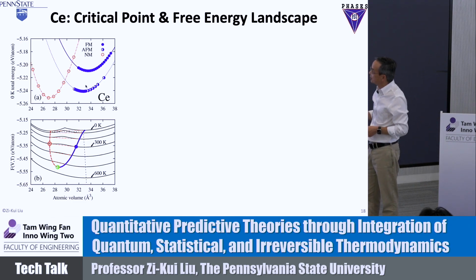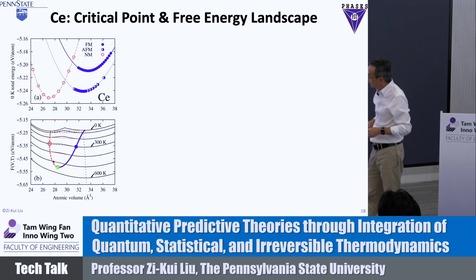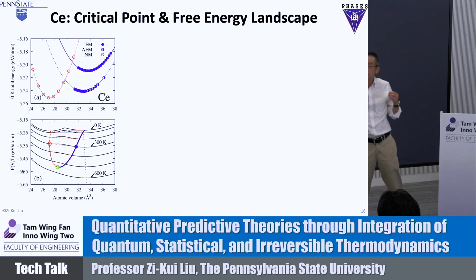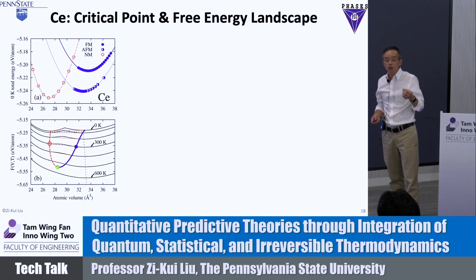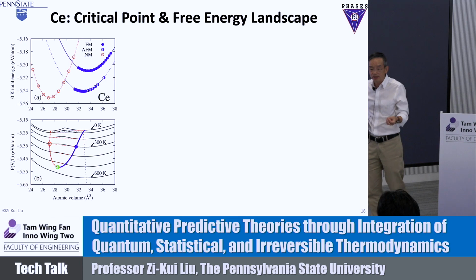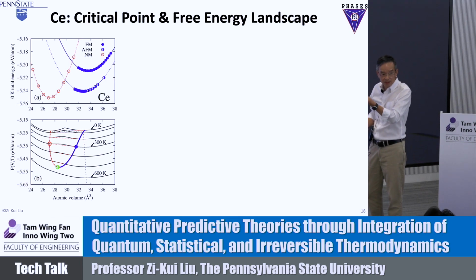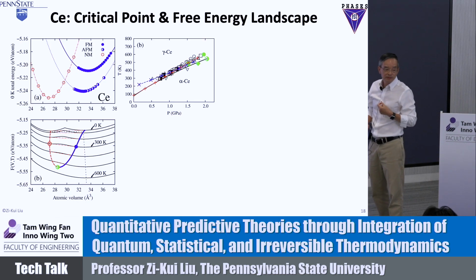With only 3 configurations, we can calculate the free energy because they're all stable. Then we put them together to calculate the total free energy of the system. At 0 Kelvin, it's a very sharp change. But as temperature goes up, because of that pk log pk term, this starts to drop until at some point the two sides become one side. That's where the critical point is, because the second and third derivatives become 0 at the same time. So with these 3 configurations only, we can predict the critical point. That's the phase diagram.